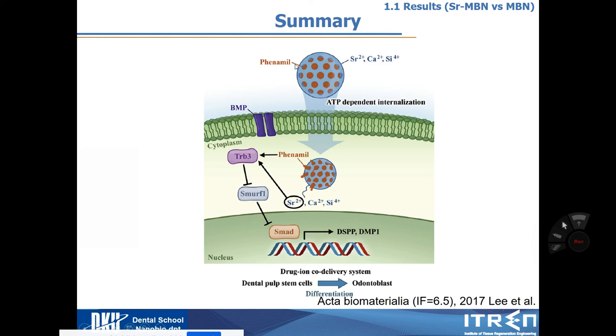As a summary, I can say that when I treat this phenamil loaded bioactive glass after doping with strontium, after this nanoparticle is taken up by the stem cell, they start to release phenamil, strontium, and calcium and silicate ions. Especially strontium and phenamil can activate TRB3, and then the TRB3 activation decreases SMURF1, and this pathway can increase SMAD, and this SMAD protein can accelerate DSPP and DMP1 gene expression, which is directly correlated to differentiation of the dental stem cell to odontoblast. So I can suggest a drug ion co-delivery system using bioactive glass for dental stem cell regeneration, which is published in Acta Biomaterialia.